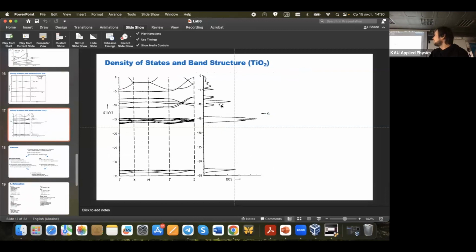From my own experience, I have calculated titanium dioxide, and with one k-point grid I got some plot, but then I increased the k-point grid to a really huge number of k-points, like 70, 70, 35 or something like this. And I got very long and narrow peaks. I didn't get it with lower k-point density.